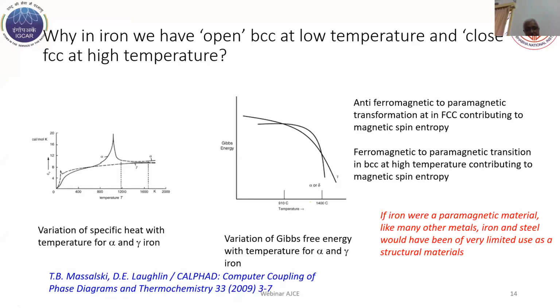Because of this specific heat variation, you get the middle graph. You can see the free energy. I don't know how much you will understand free energy, but free energy is the energy which determines which phase is stable at a given temperature. We can see the free energy curves for both austenite and ferrite, or what we call gamma and alpha. They cross each other, and at low temperature we find the ferrite phase is stable because it has low energy. At high temperature, the austenite phase is stable because it has low energy. And when you go to still higher temperature, above 1000 degrees centigrade, we find again the ferrite phase is stable. This is coming because of magnetism present in the steel.